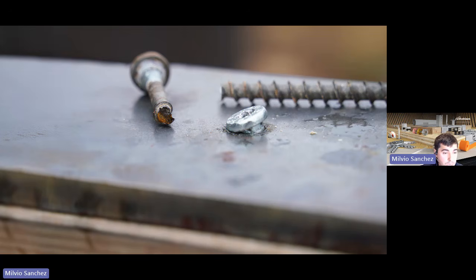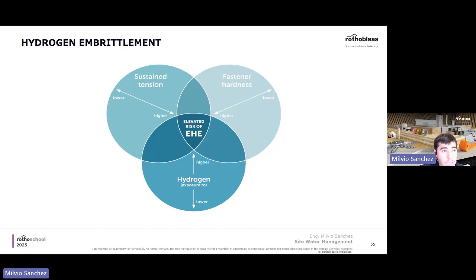So premature failures may occur, which means a failure that is below the expected failure zone. One of the conditions could be hydrogen embrittlement, which is fairly associated with moisture on the job site, pretty much the exposure to hydrogen. Also, it's a matter of how big your sustained load, your sustained tension, is, and the fastener hardness. Environmental hydrogen embrittlement means the one that happens outside on the job site. So the bigger the sustained load, the bigger the hardness, and the bigger the hydrogen exposure, that is a sweet spot where all three combined may create brittle failures.